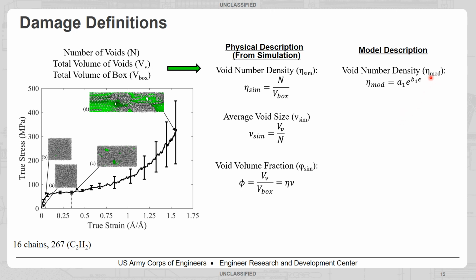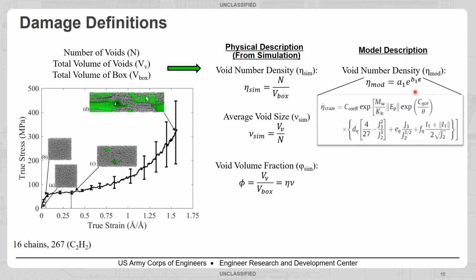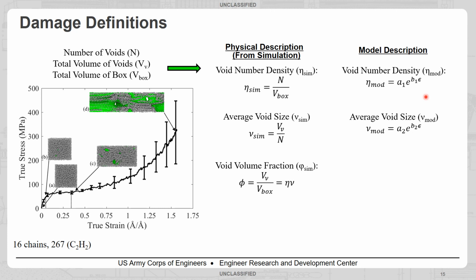For the model, we use an exponential growth law for nucleation that's typically used in the literature. Here, A1 and B1 are shown as simplified constants, but they can be quite complex. For example, in the parentheses you would have B1, which has both temperature and stress state dependence, where you have nucleation in tension or shear or compression, if by chance your polymer forms voids during compression, which is rare, but it is possible. Here we have the average void size, again defined by exponential growth. And then we introduce a term called the coalescence fraction, which is a logistic growth equation. This allows us to capture the downward trend in the number of voids. There's a certain point in your simulation where the number of voids will begin to decrease as voids start to merge and coalesce into larger voids. So this allows us to capture that.